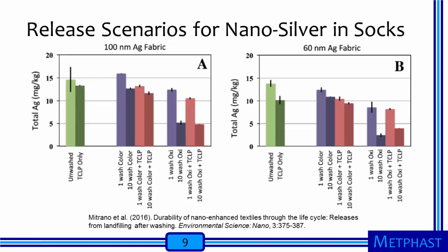The figures show the mass of silver present per mass of fabric on the vertical axes versus test conditions on the horizontal axes. The figure on the left shows results for fabrics treated with 100 nanometer silver particles, whereas the figure on the right is for fabrics treated with 60 nanometer particles. Washing clearly removed silver from the fabrics. In all cases, 10 washes removed more silver than a single wash cycle. The detergent with the oxidizing agent removed more silver than the detergent with no oxidizing agent. More silver was removed from fabrics with the 60 nanometer particles than ones with 100 nanometer particles. In general, the TCLP protocol suggested that silver might still leach from the treated fabrics if they were deposited in a landfill even after 10 wash cycles.